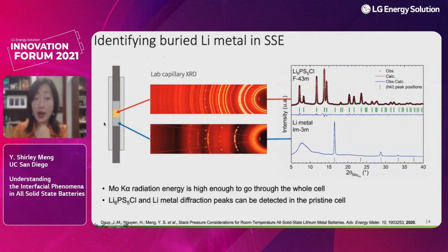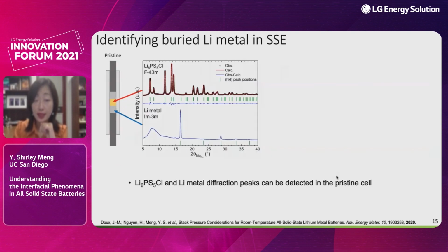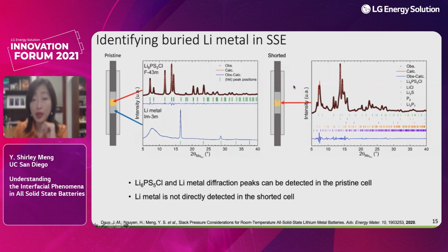So in my group, we set up this kind of capillary cell where you can put two lithium anodes on each side, and you have the solid electrolyte in the center. And with this very beautiful lab scale XRD, you can obtain very nice refinable X-ray data where you see the center is beautiful argyrodite electrolyte, and on both sides is the polycrystalline lithium metal. And when we start to cycle the cells, this technique can be used to peek into the buried interface and help understand what is being generated.